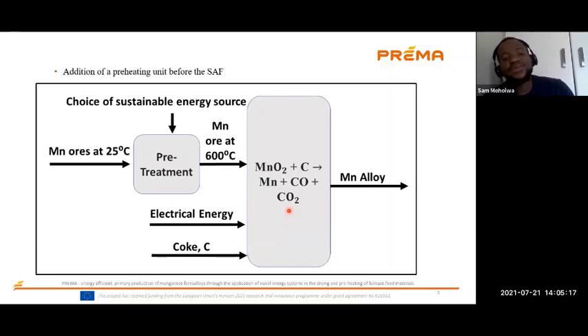Then the process then looked like this. We have a manganese ore which is being preheated in a preheating unit, maybe a rotary kiln, a shaft kiln, but in this case we'll be focusing on the rotary kiln. Then we have this preheating unit being provided energy from a sustainable source of energy, maybe solar, maybe wind energy, maybe hydro energy and the likes. So this manganese ore will be preheated to 600 and fed into the SAF as usual. Then we have the coke and the fluxes being fed into the furnace. Then we add energy to melt the reactant so that we can get our product, which will be Mn alloy, some slag and some gases.